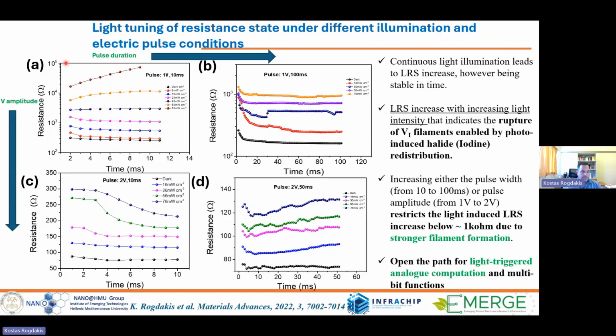Then, very briefly, we can tune the resistance state by light illumination. In this graph, you can see by increasing light illumination, we can increase the resistance from low values to high values almost in an analog fashion. So we can have a linear control of the resistance state by changing light illumination. So we demonstrated an optoelectronic memristor that is tunable, of course, by electrical pulses, but also by light pulses.